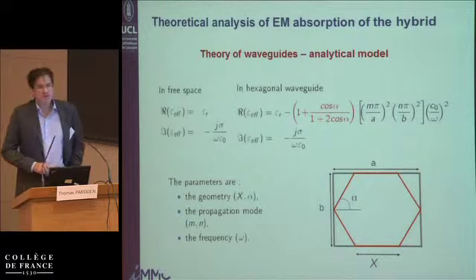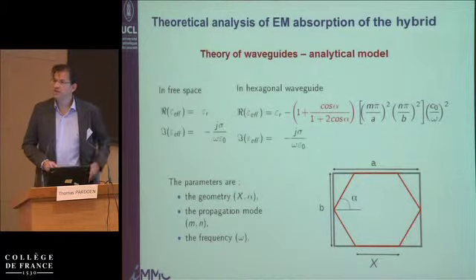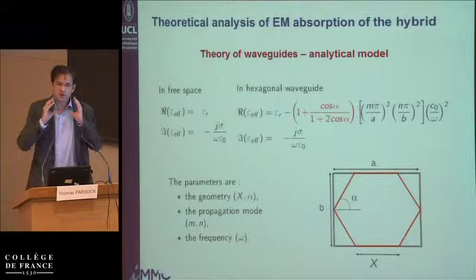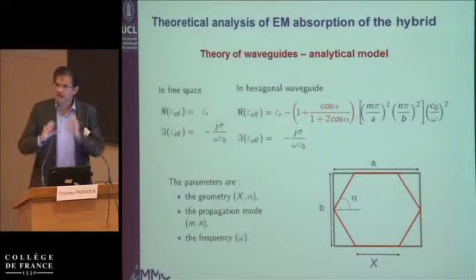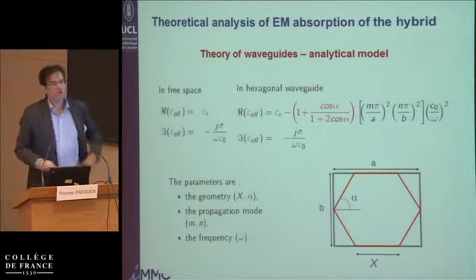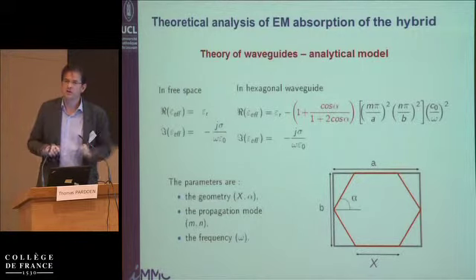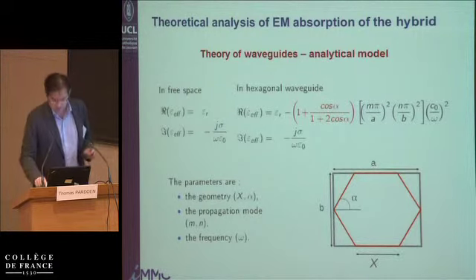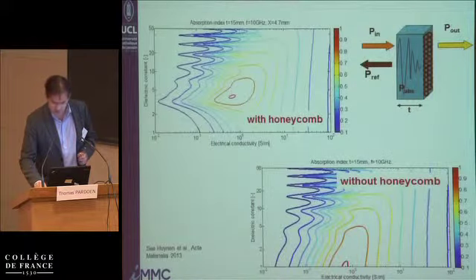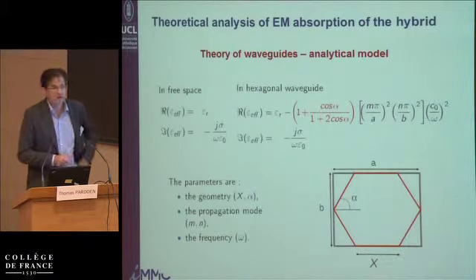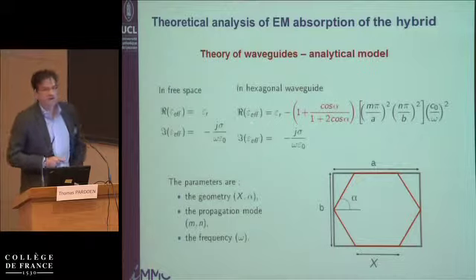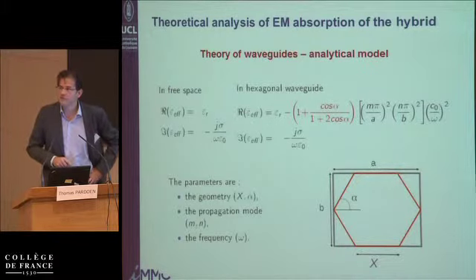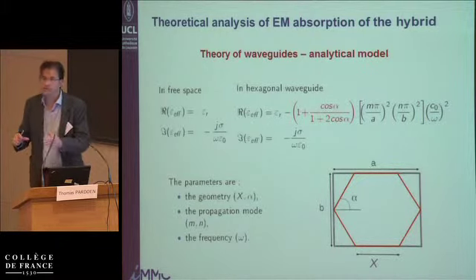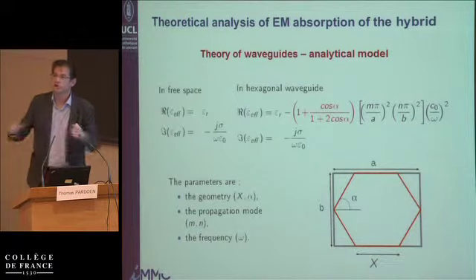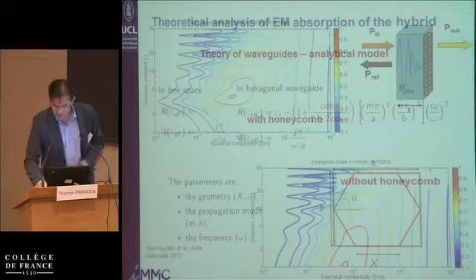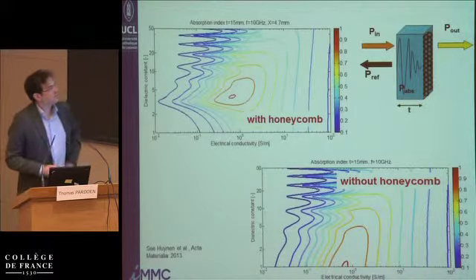efficiency. And the reason comes from a waveguide effect. The aluminum honeycomb is playing the role of a waveguide, and by this effect, is sort of reducing the dielectric constant of the medium. I will not enter into the details, but once again, we can get a closed form expression for the new effective dielectric constant of the medium, and so the material is not a complicated material, it's a foam with carbon nanotubes inside a honeycomb, okay? It's all analytical, and the result is the following.